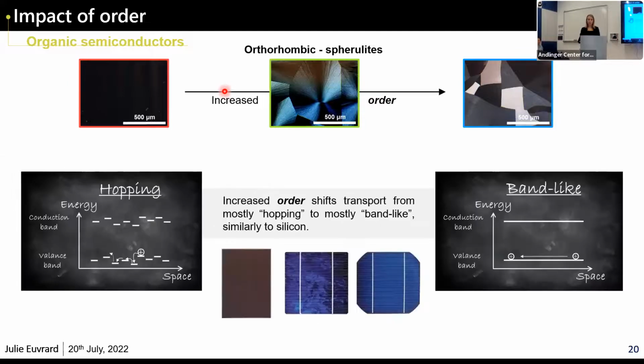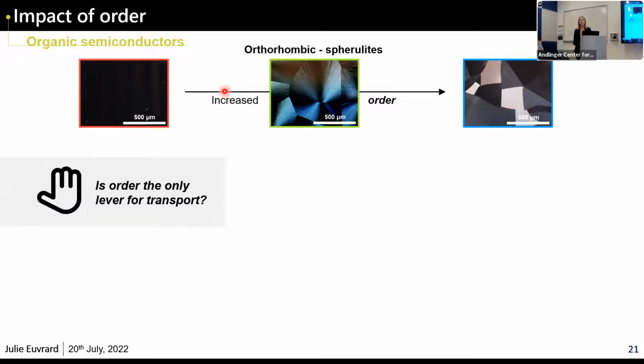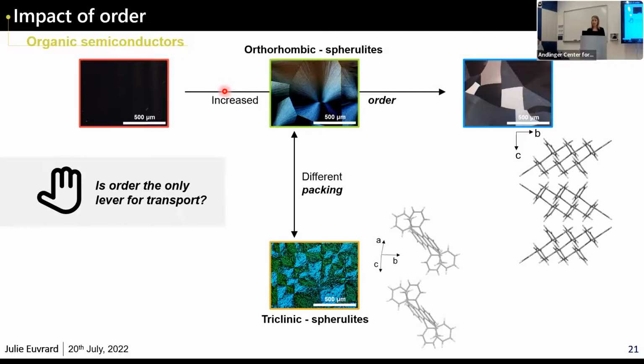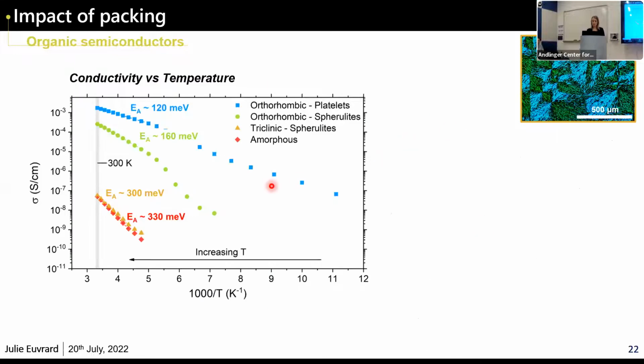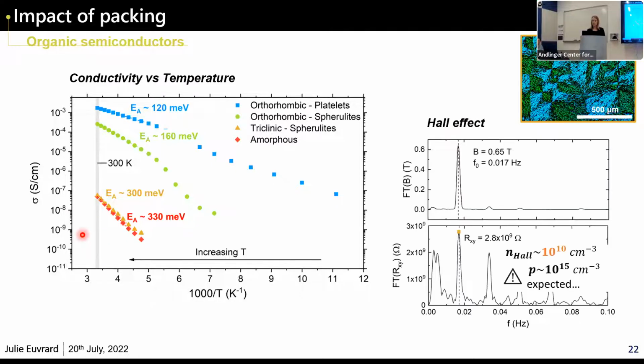Okay, now there's something we cannot do with silicon, which is change the way the atoms pack. At ambient pressure and temperature, crystalline silicon will only form in a certain crystal phase. Now, in rubrene, you can actually have different crystal phases. So you can also look at how packing can impact transport. So as I said, here you have a certain packing, which is different from the packing here. And when we look at the transport properties, we observe that actually, surprisingly, the data are very similar to amorphous. Here you have in orange the triclinic. And the same thing happens in Hall effect. We obtained very similar data between triclinic and amorphous rubrene.